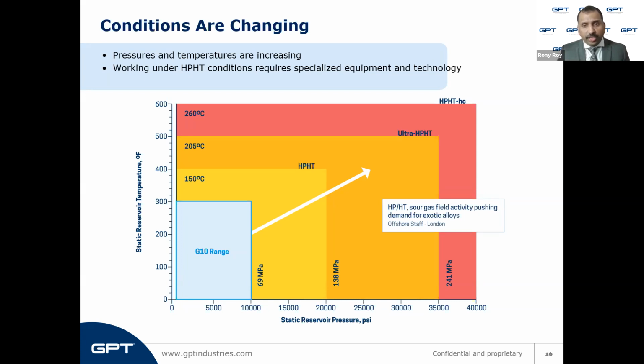Metal coated GRE should not be used in applications that are over API 10K, and fire safe glass reinforced epoxy, or GRE, should not be used in applications over API 5K. As we just saw, G10 covers very little of the potential temperatures in the previous slide and pressures that can be seen in today's pipelines. G11, another grade of GRE, which has a better temperature rating, is also slightly better with a temperature limit of 200°C, and it covers only a small portion of this graph.